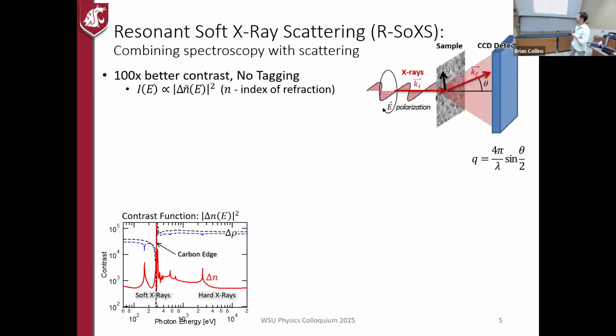So we turn toward resonant soft X-ray scattering, which you can see here. We're just coming in with a collimated beam. It's going through the sample and then scattering into an area detector. And the scattering pattern we get here is encoding the nanostructure at a statistical level. Mathematically, the scattering pattern, using the Born approximation, is a Fourier transform of the real-space distribution of structures. And so we can extract that information through that conduit.